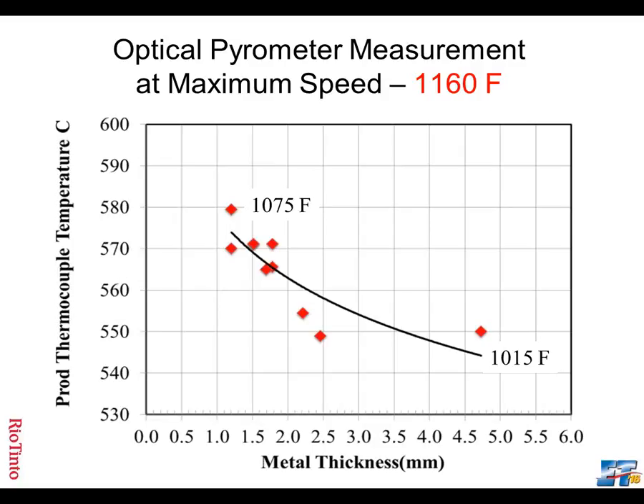However, it did seem to vary with profile thickness. It's an interesting observation. For example, if we want to run a profile which is, say, 60 thou wall, 1.5 millimeter, as fast as we can, we should be looking at a pyrometer value of about 1075. If we run a profile which is 5 or 6 millimeters thick, we really can't go much above 1015 Fahrenheit because we're going to produce a melted surface. This tells us that there are some interesting relationships.